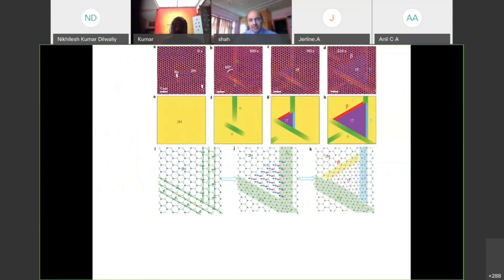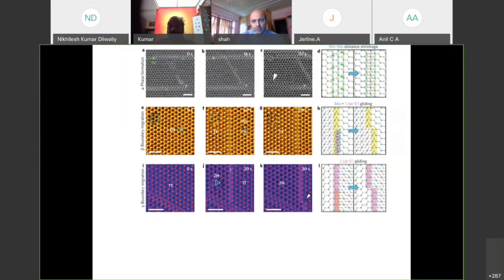See, for example, a group has just taken a 2H structure of this molybdenum sulfide, and then they have added one single atom of ruthenium. And then you see here, they have taken a transmission electron microscope, and with the transmission electron microscope, they show that it forms 1T, which means a trigonal structure. And then when they allow more time, you see they are able to make a trigonal structure of larger dimension, which means the atoms are getting disturbed and therefore the trigonal phase formation occurs. So this is a very interesting thing in the sense you have a molybdenum sulfide and you put one atom of ruthenium and then you have transformed that given area into a different crystal structure for reasons of crystallography.